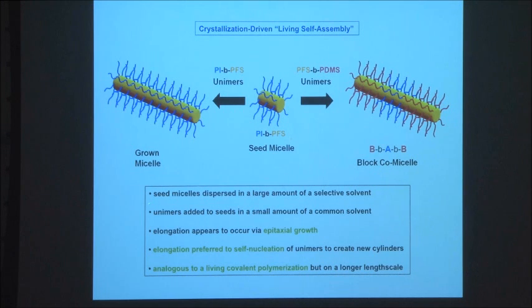So how do you do this? You take the seed micelles dispersed in a large amount of the selective solvent, such as hexanes. You add the unimers in a small amount of the common solvent, THF. The elongation appears to occur by epitaxial growth, by crystallization of the dimethyl PFS blocks on the ends of the pre-existing seed cylinders. Very importantly, this elongation process seems to be infinitely preferred to self-nucleation of the unimers to create new cylinders. You can imagine these unimers, when you add them to the seed micelle solution in the selective solvent, would actually form new cylinders.